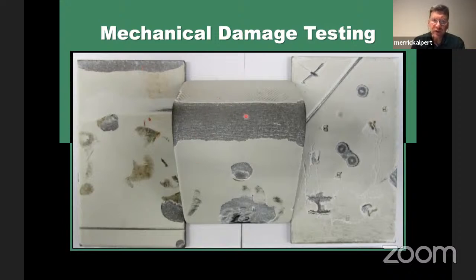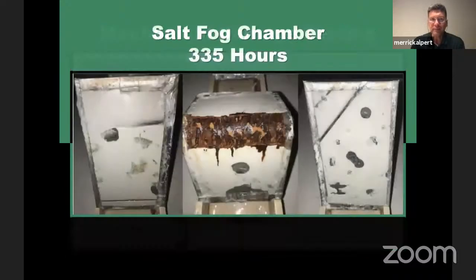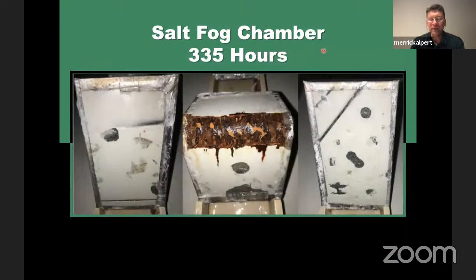They knew that here, where they're exposing the fresh carbon steel, they're going to see corrosion. But they want to see, can you maintain that true edge? Can you maintain that line? Or is it going to peel back the way that paint would? And then you see with hammers and chisels and saws, they've simulated mechanical damage by trying to tear away the ceramic. They then put those panels into the salt fog chamber for 335 hours.